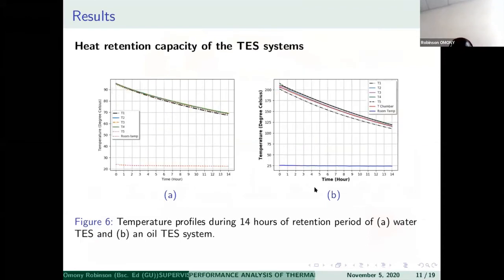Then during the heat retention process, the storage was charged. Both the water test and the oil test were charged to maximum temperature. Then they were allowed to stay over a 14-hour period while monitoring the temperature inside. So this point corresponds to the maximum temperature attained after charging. Then after the 14 hours,